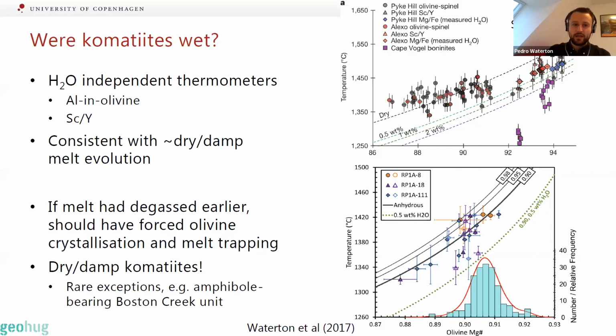The other big advance has been thermometers that are independent of water contents. And most notably, these are the aluminium in olivine thermometer, which works on aluminium exchange between olivine and chromite, and the scandium yttrium thermometer. So these are consistent with fairly dry or damp melt evolutions. And I've got a couple of plots on the right. What these are showing is a plot of temperature against the olivine forsterite content. Essentially, you can plot out curves for how you'd expect this to evolve if you had a completely dry liquid, one with a bit more water, or one that's fairly wet.